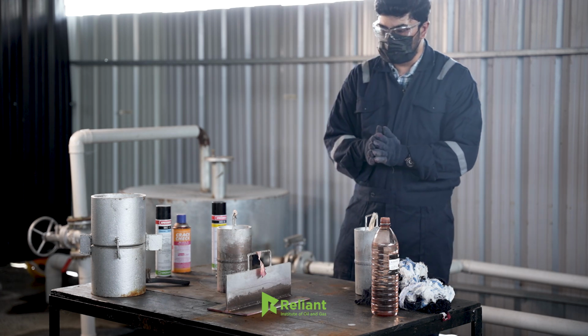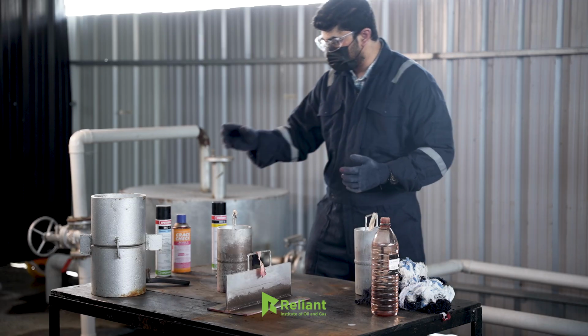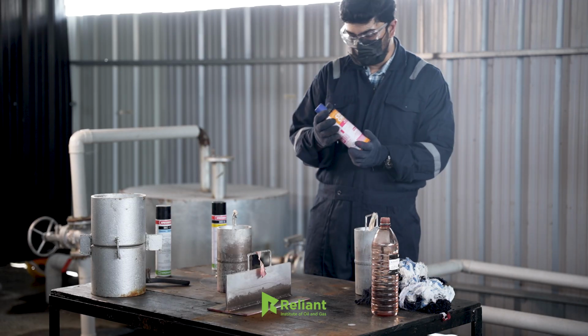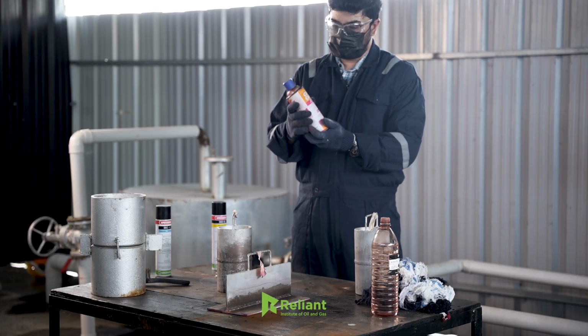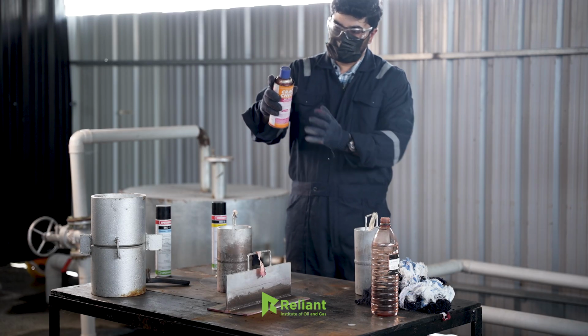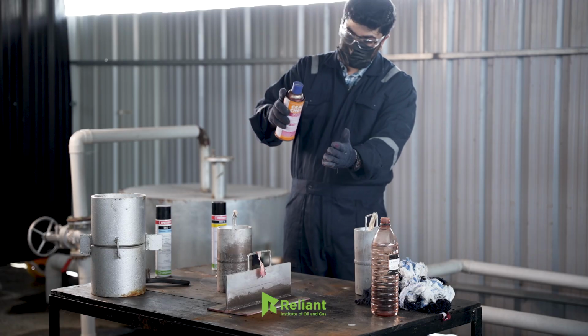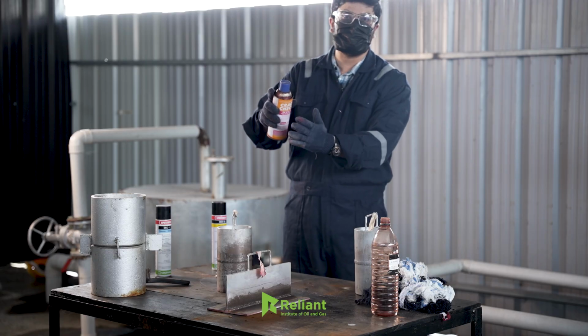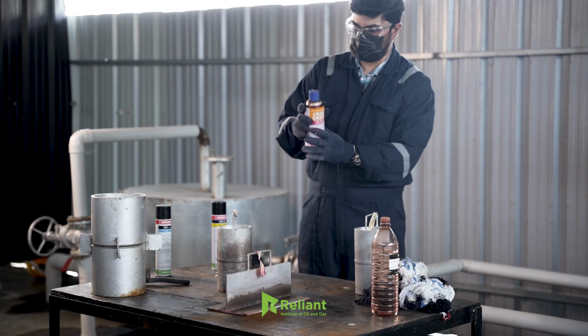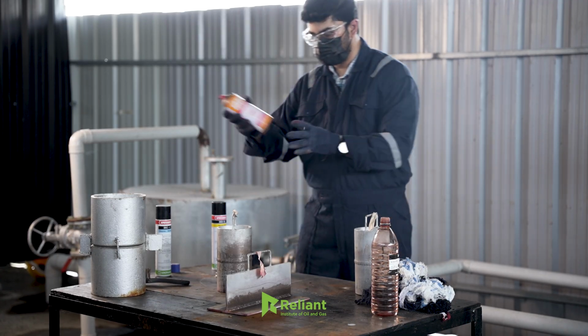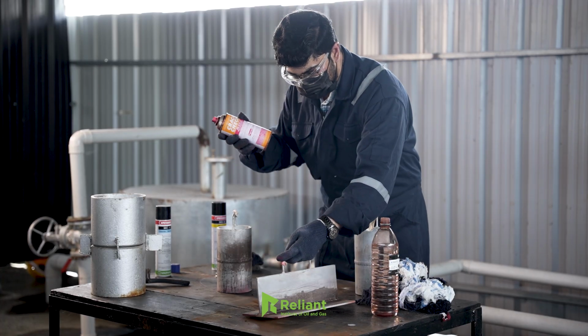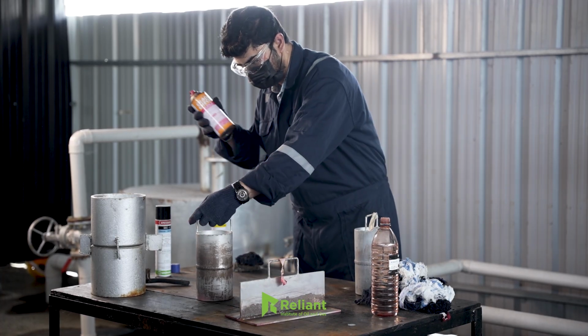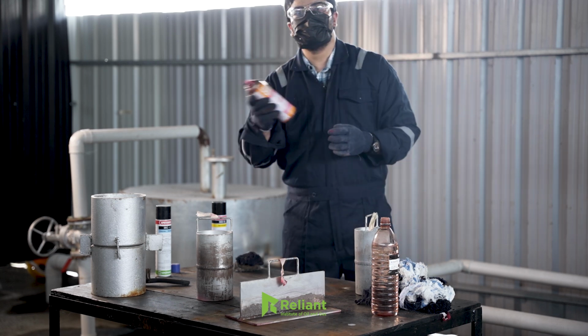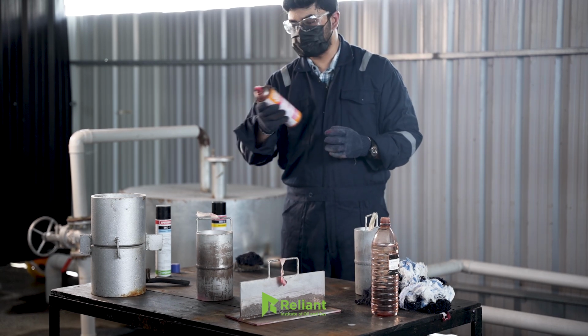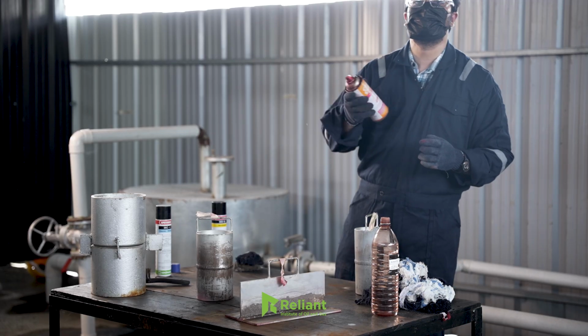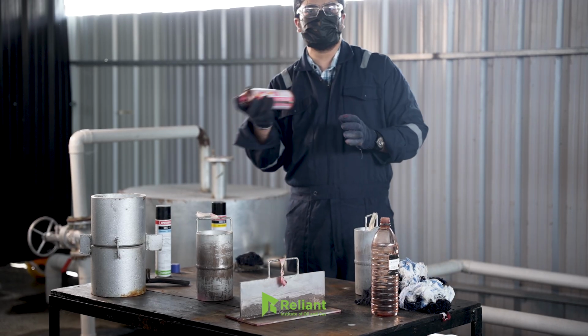Now I'm going to apply a penetrant. So while applying the penetrant, it is very necessary to follow that the penetrant should be placed at a 45-degree angle, and at 1 feet distance from the test piece we have to apply the penetrant. So just one layer of spray is sufficient for the penetrant to interact with the material due to the higher capillary action.